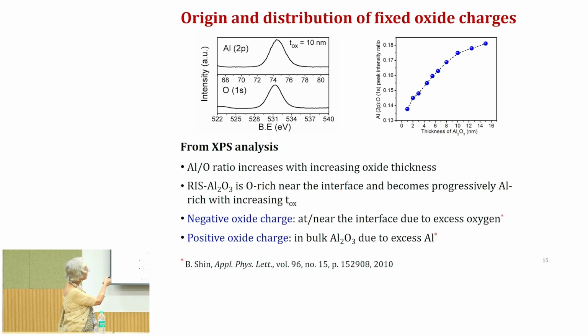So, if you look at this, you will find that as the thickness of the aluminum oxide increases, you see how the composition changes. That is why the negative charges are located very close to the interface. You see they are located within about 2 to 3 nanometer, and beyond that you find that the aluminum to oxygen ratio is actually increasing significantly.